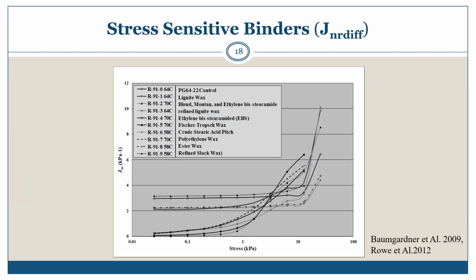This figure exhibits stress-sensitive binders to show the importance of the JNR diff specification limits in M332. The wax-modified binders represented in this figure have very small JNR values at 0.1 kilopascal level, but at 3.2 kilopascal lose significant stiffness. This wax study was one of the drivers to include JNR diff in the binder specification to limit the types and amounts of waxes that could be used to modify asphalt binders.